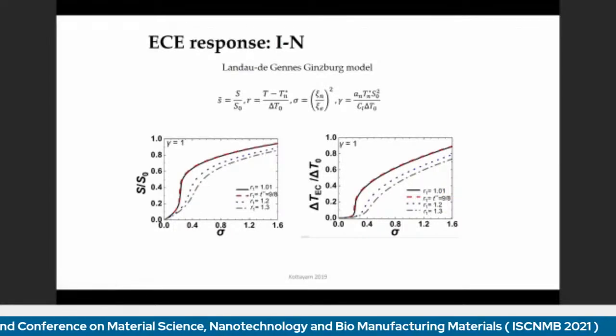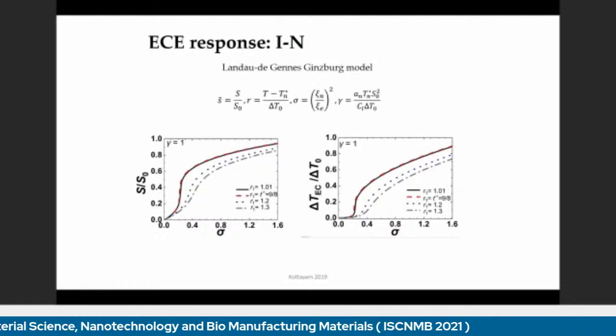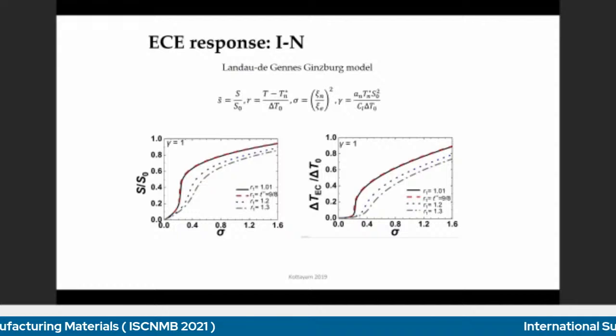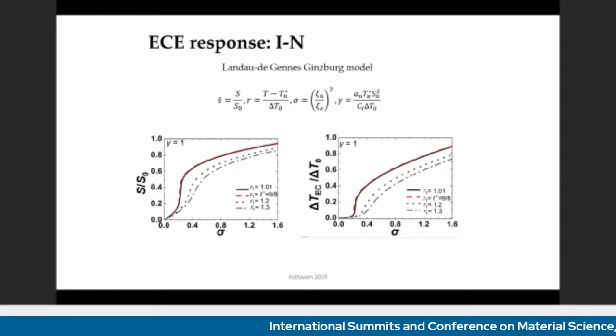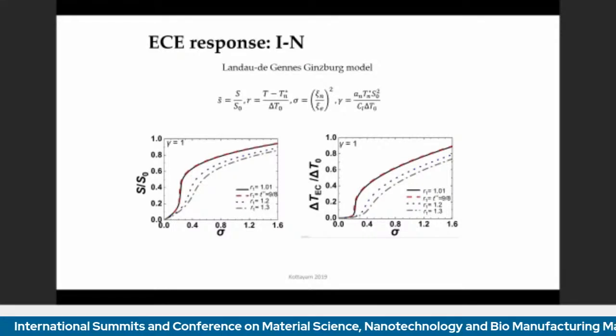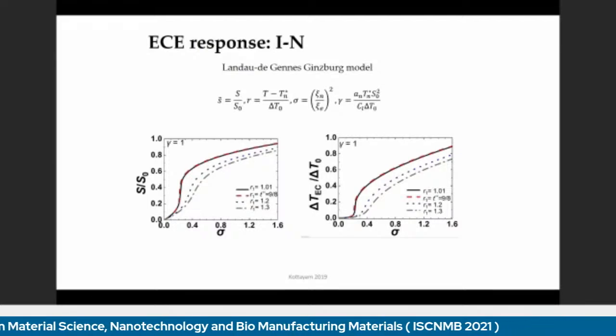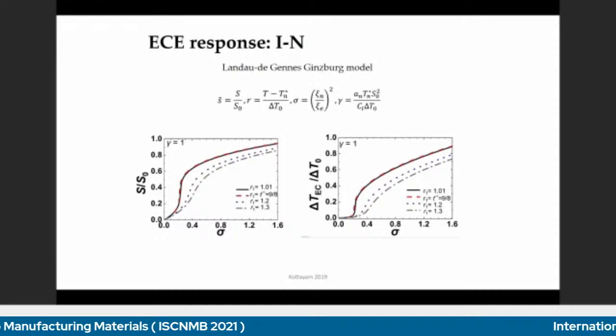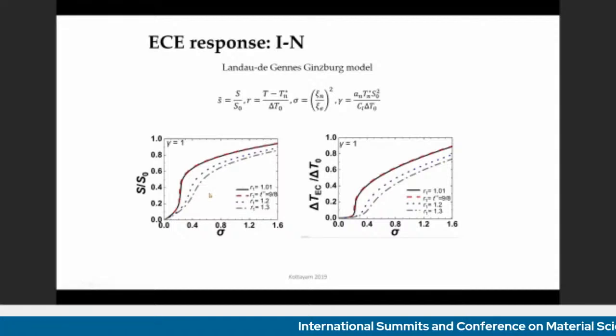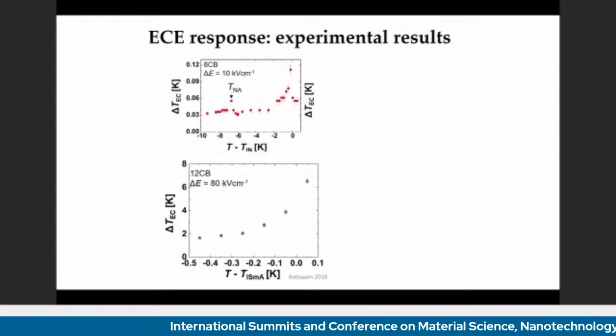In theoretical analysis, we prove that the strongest possible response is also near the phase transition. We have studied the transition from isotropic to smectic phase, but we have just preliminary results. The results suggest that the direct isotropic to smectic phase could give us an even better ECE, electrocaloric effect, response. So now we go to the experiment.